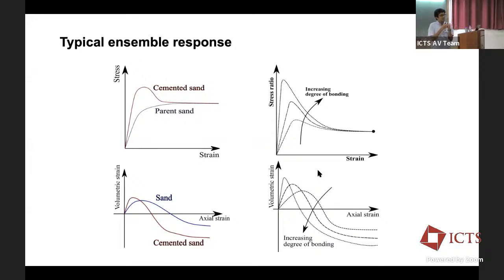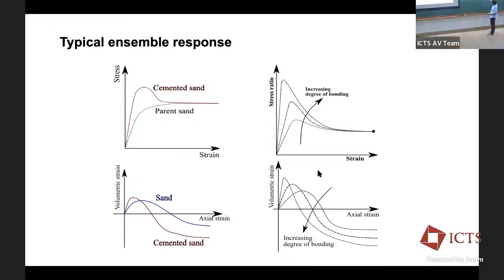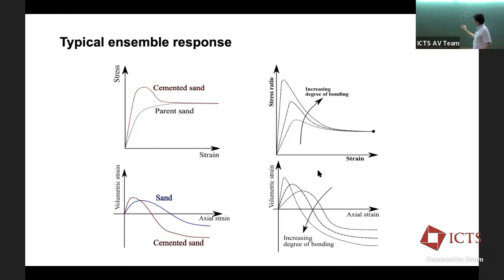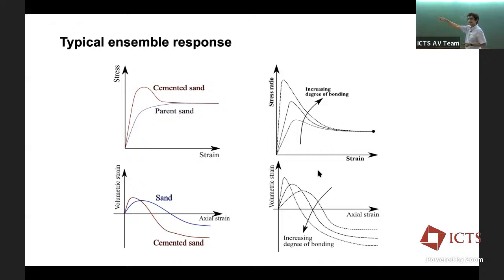When cohesion exists between particles, think of each glass bead as surrounded by a layer of cohesion. When you break the system down, you end up with particles that are slightly larger in dimension than the original glass bead, and the overall system size is slightly different. So I can never exactly replicate the volumetric strain curves of the parent material. The stress state, however, will eventually recover the parent sand stress state — but the volumetric strain will not.